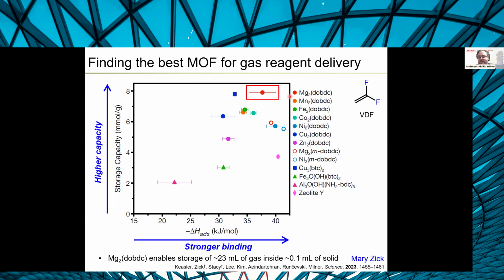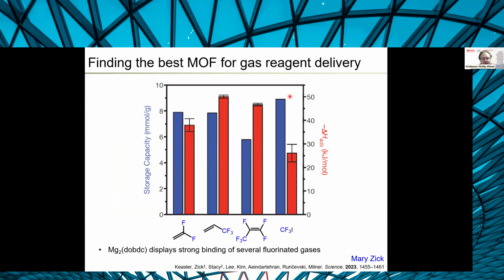And I think what's remarkable about this approach is the significant volume compression that happens inside of MOFs. So we can store 1 millimole of gas, which would normally be a relatively large balloon, 23 milliliters, in just maybe 100 or so milligrams of MOF, or 0.1 milliliters of solid. This MOF is nice because it actually binds a range of fluorinated gases quite strongly. Mary showed over the course of her PhD, this seems to be a universal thing, that this MOF is particularly good at binding fluorinated molecules with strong enthalpies of adsorption as well as high capacities.